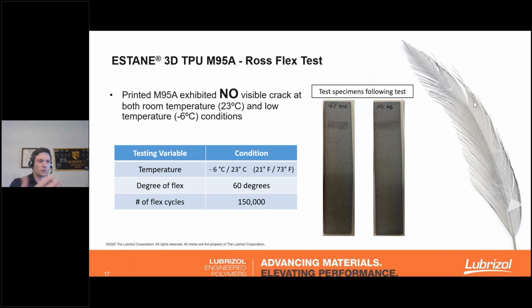in a general sense. So the samples you see on screen were actually flexed to 60 degrees for 150,000 cycles at both -6 degrees Celsius, so below freezing, and 23 degrees Celsius, so about room temperature. And both the parts made it through with no cracks, damage, or failures. While this might be applicable mostly to the footwear industry, it is a testament to how robust this material can be while remaining flexible.